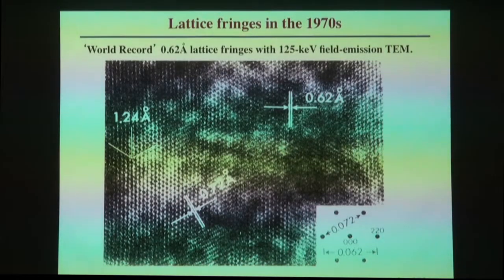So this is an old picture, but it is an indication, even at 100 kV, of Tonomura's work way back in the late 1970s. You can see the vertical lattice fringes here of 0.62 angstroms, actually 125 kV, I beg your pardon, a 125 kV field emission electron microscope. For this microscope, the point resolution, the instrumental resolution, was about 3 angstroms. But if you get the right operating conditions, you can get very fine lattice fringes.